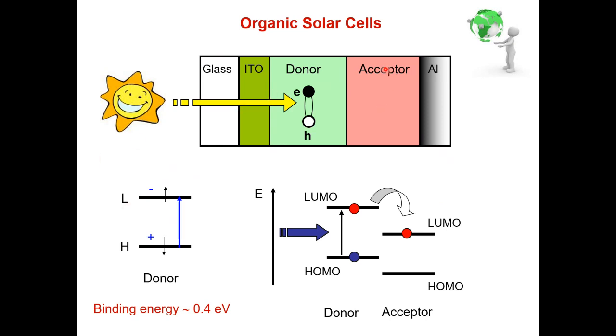And the trick is to use a second material that we will call the acceptor. And basically, when you excite one molecule, you generate your excitation. Then the excitation has to move, to migrate, and to reach the interface with the acceptor.